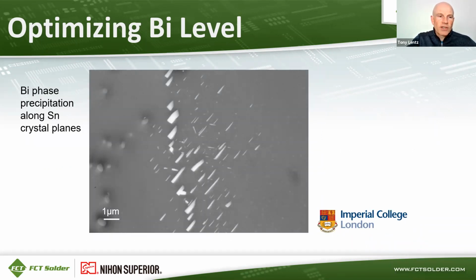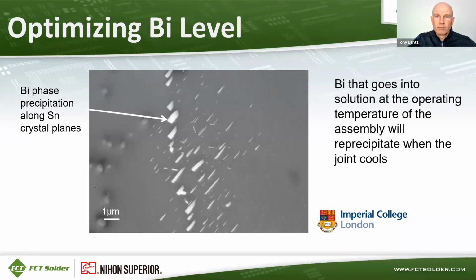This is another cross section that shows that bismuth tends to precipitate along the crystal planes. So the bismuth might fully dissolve at the operating temperature when the solder is molten, but then as it cools down, it will reprecipitate as bismuth islands.